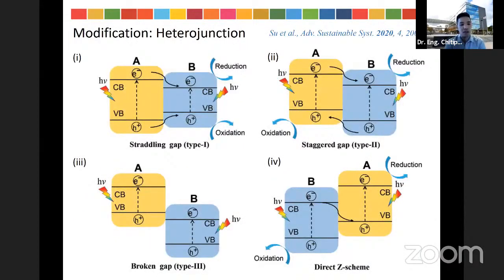So here I show the general four types of heterojunction. In type 1, the band gap energy of material A is larger than the band gap of material B. So under light irradiation, electrons are excited in both materials. The electron and hole from material A are transferred to material B. In this case, the recombination of the electron and hole should happen in material B. So it's not so good to make this heterojunction because it cannot avoid the recombination in material B.